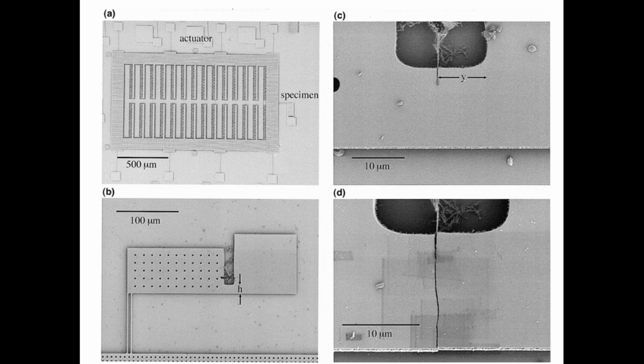Okay, so after all that incredibly careful work, the on-chip design, the sharp cracks, the annealing, the displacement measurement, the FEA, what did they find? What's the number? The headline number, the median fracture toughness value they obtained, was 1.1 MPa·m^(1/2). 1.1. How does that compare to previous work? Well, they noted it's generally lower than the values reported in those earlier studies that used the micromachined notches. So those less sharp notches might have artificially inflated the toughness values. That's the implication, yes. Interestingly, though, this 1.1 value is actually quite close to the fracture toughness values that have been reported for single crystal silicon.